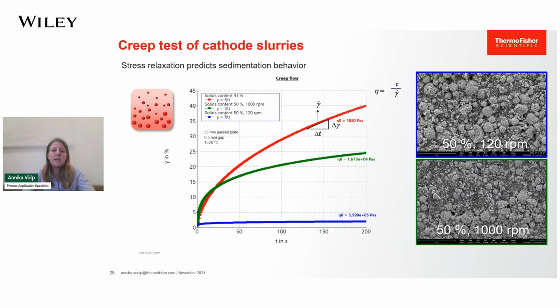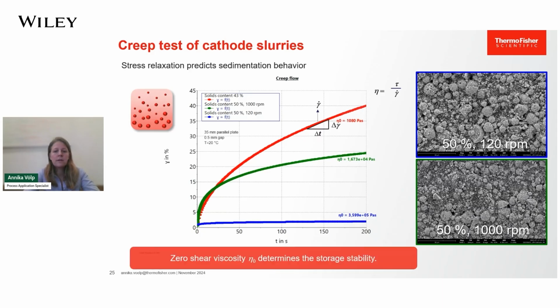Another way to study stability is a creep test. The slurries are subject to a constant stress and the deformation is measured as a function of time. After a certain time, a linear deformation response becomes apparent. The slope of the deformation versus time, hence the first derivative, is the shear rate. The zero shear viscosity can be calculated as the ratio between the applied stress and the shear rate gained like that. The lower the shear viscosity, the lower the storage stability of the slurry, of course.